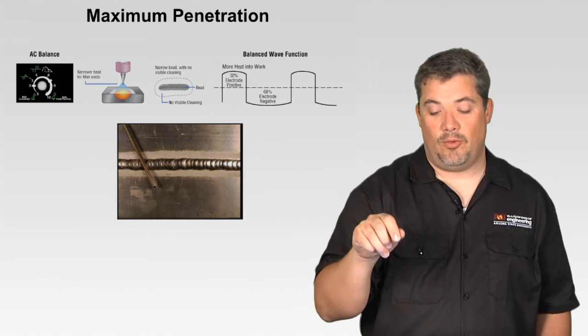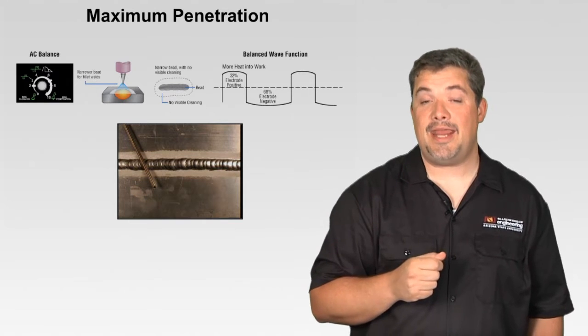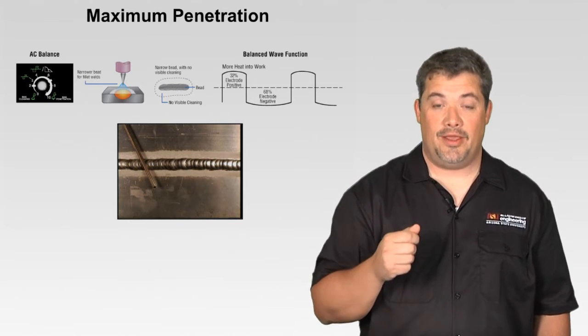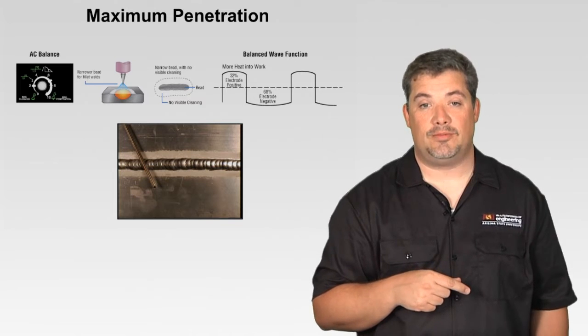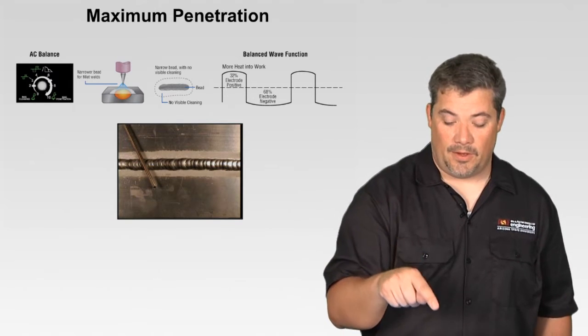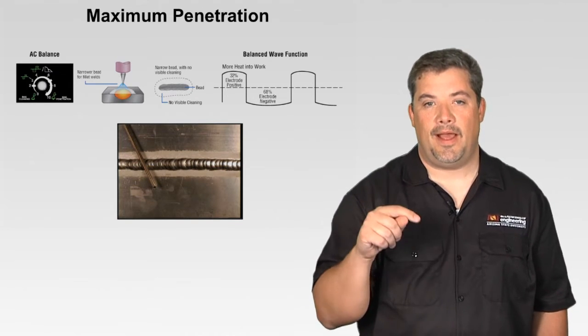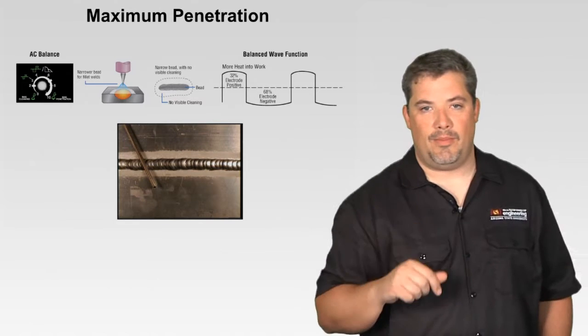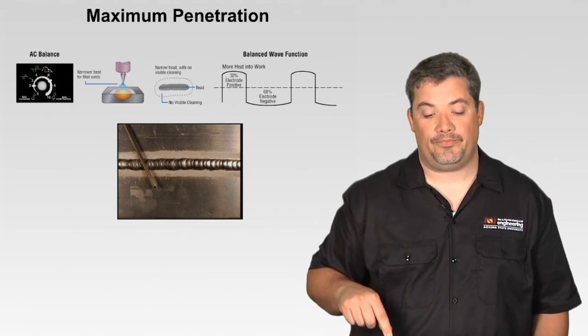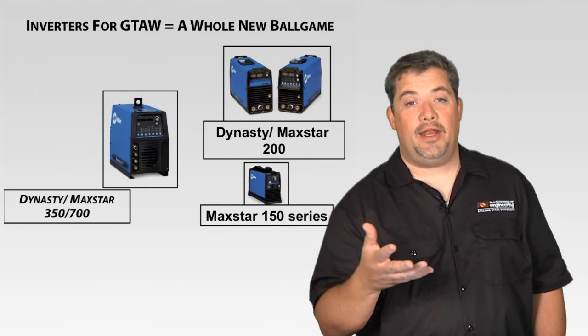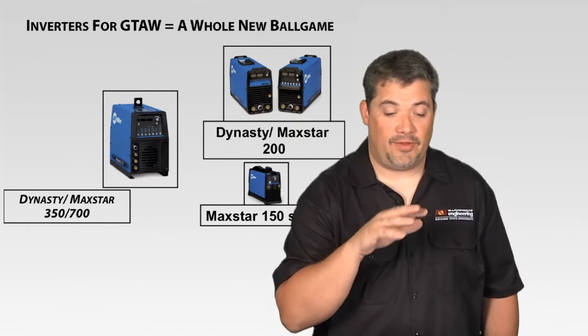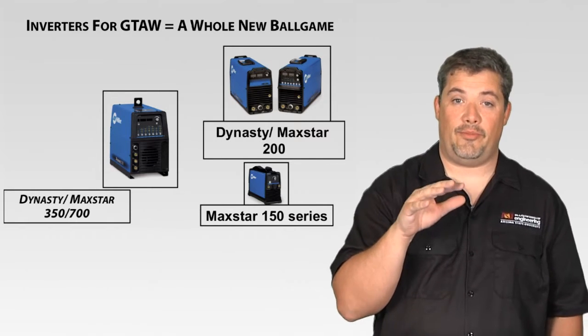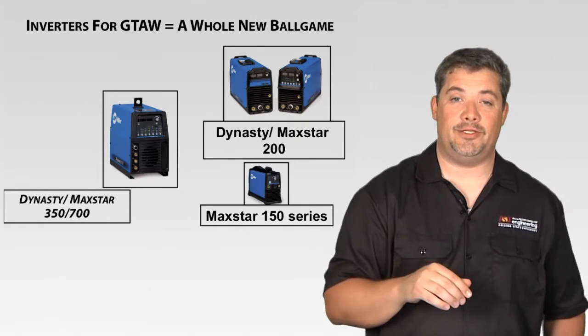In this case, when I turn this to 68% electrode negative, you can see there's a much smaller ball on the tungsten now. The etching zone is reduced. I'm putting more heat on the part, and I'm minimizing how much etching is occurring. But now we get into advanced AC. That was the conventional basics that occurred from AC to DC in TIG welding in general.